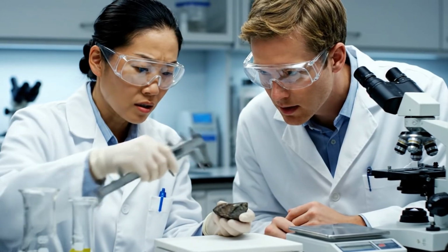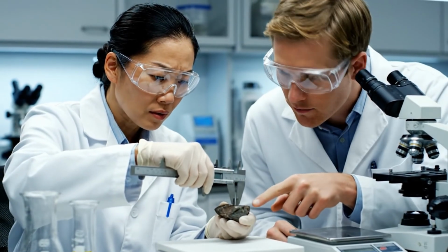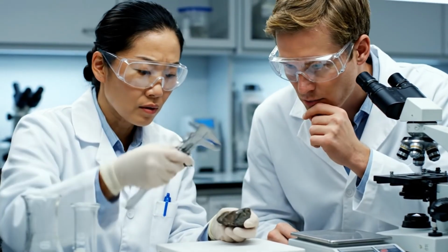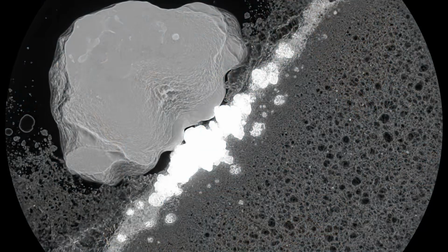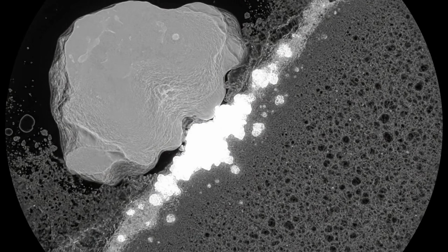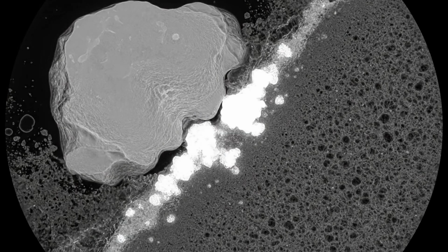Standard Portland cement concrete reaches 70% strength in 7 days. The hot mixed concrete took longer initially, which worried the team. Maybe hot mixing was just dangerous without being better. But at 28 days, something remarkable appeared under the microscopes. The lime clasts had created ultra-dense zones at their boundaries. These zones were denser than anything in modern concrete.